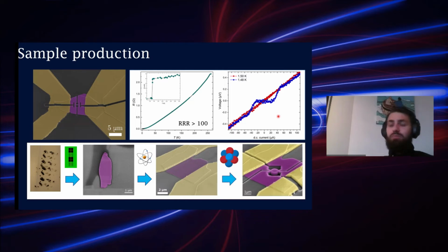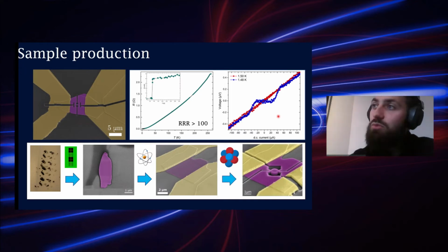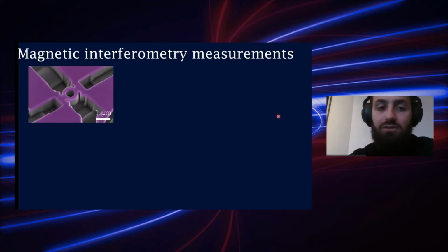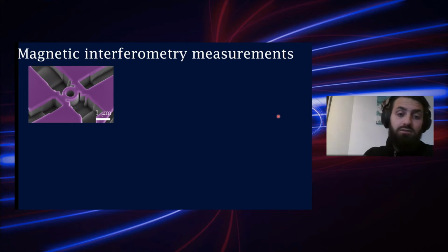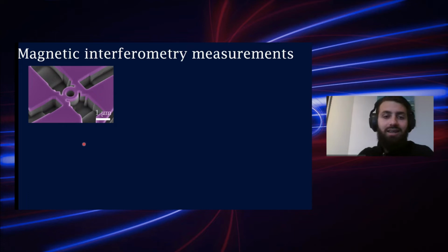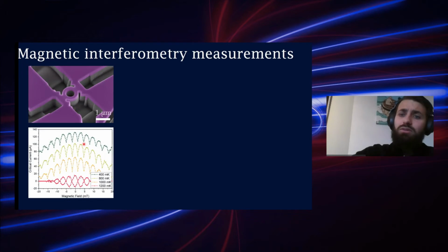All right, so now we can make all sorts of microstructures that have high quality. The one I will highlight first is the ring geometry. Since if you have a ring geometry of an ordinary superconductor, so no unconventional superconductivity, no domains whatsoever, and you would thread a magnetic field through the center of the ring, you would not see any interesting behavior. However, this completely contrasts with what we see.